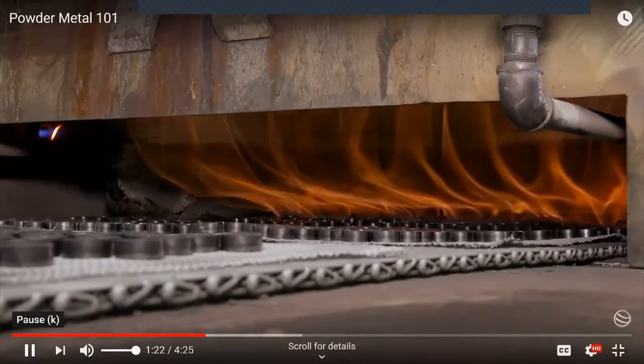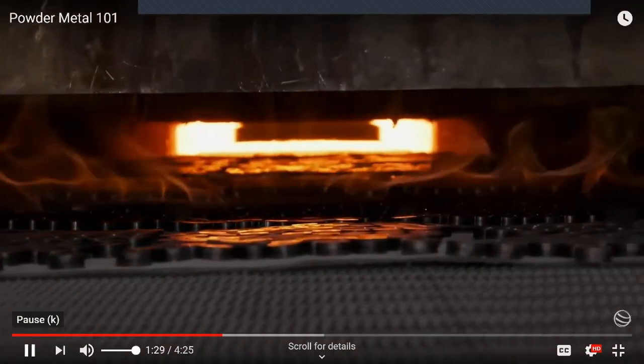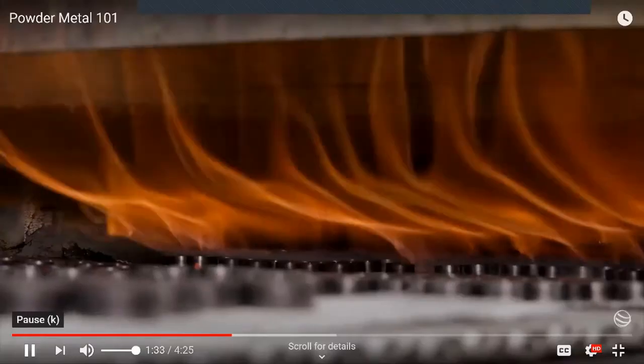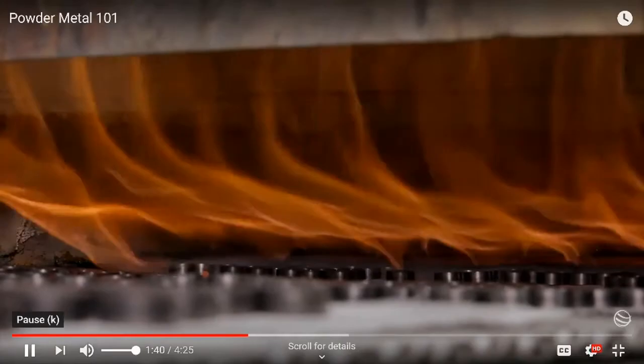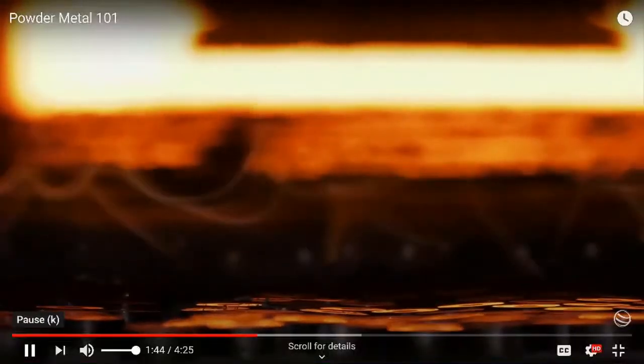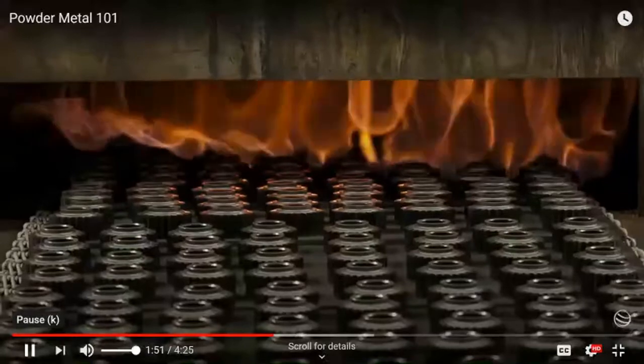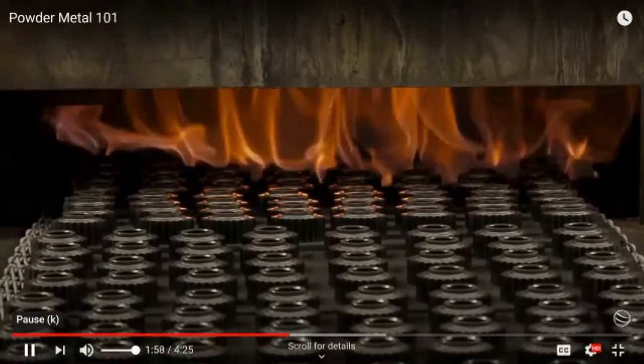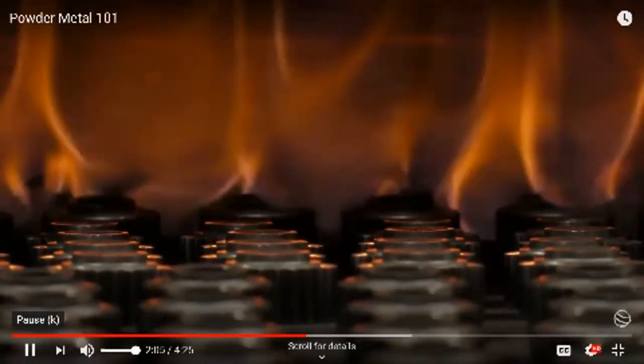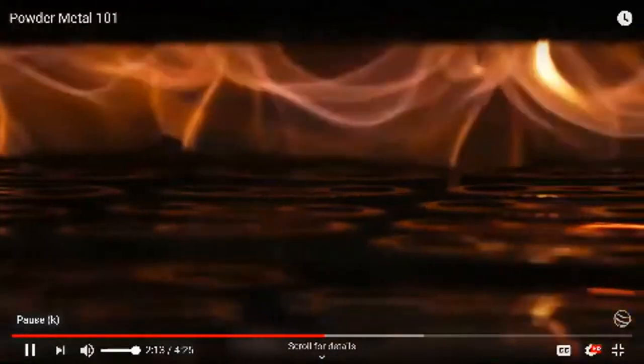Many complex phenomena occur in the sintering furnace. For steel, temperatures will be in the 2000-degree range. Nitrogen is used as a protective atmosphere; hydrogen is used as a deoxidation or reducing atmosphere to take oxides off the metal particles. First, the lubricant is removed in the preheat sections — we only needed it to eject the part from the die. As temperature rises in the higher sections, we get particle-to-particle bonding, alloying from one particle to another, reduced porosity, and we build the strength needed in the end product.